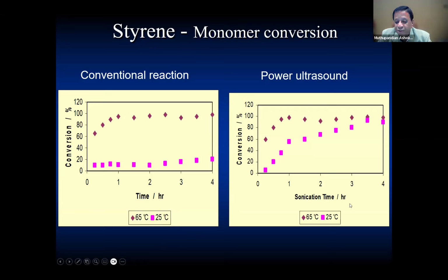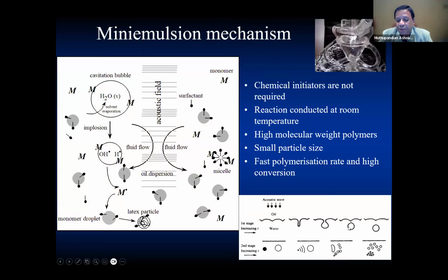Whereas if I use the sonication process, where we are creating radicals that are used for making the polymers, you can see that even at 25 degrees Celsius, I can achieve 80 to 100% conversion, which means for those polymers which are heat sensitive, the sonochemical method is better than the conventional thermal method. And this is the mechanism involved.